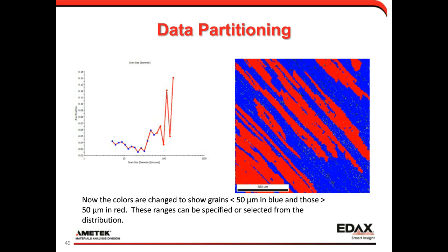So here now I can go into the software and adjust my color scale. Rather than going across a complete color spectrum, I've just gone blue to red to make a two-phase, or two-categorical, distinction between grain sizes. In here I've said if it's less than 50 microns, I'm going to shade them blue. If it's greater than 50 microns, I'm going to shade them red, and apply that color scale. So here I've differentiated by a 50 micron selection.